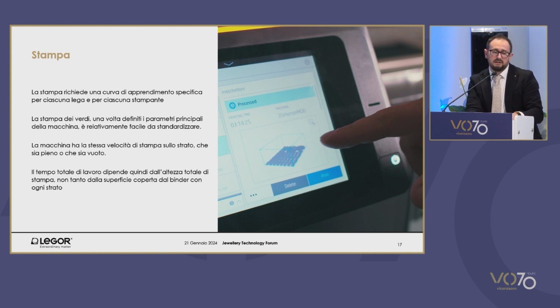Our experience with the different printers tells us that depending on the type of material, on the granulometry, and the printer that we're using, it is necessary to have a learning curve which is specific for that given setup. So after tests have been concluded, we can say that the printing phase is not the most complex one of the whole process, because the heat phase, the debinding and sintering phase, is much more surprising and has required many more iterations to achieve satisfactory results.